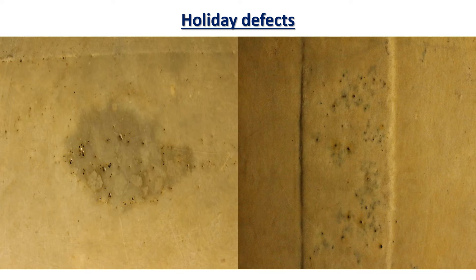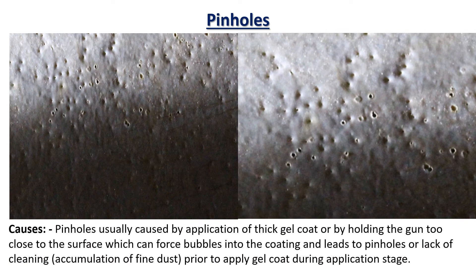Many of these defects are not seen by the naked eye, but they can be located using holiday detection equipment. Pinholes are usually caused by application of thick gel coat or by holding the gun too close to the surface, which can force bubbles into the coating and lead to pinholes. Lack of cleaning, such as accumulation of dust particles prior to the application of gel coat, also creates pinholes on the surface of the lining. These pinholes on the top layers allow the stored product inside the tank to penetrate to the underneath layers, gradually damaging them.